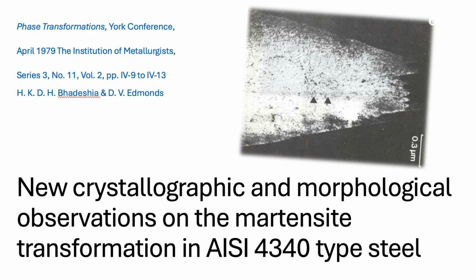Twinning. The sources found twinning within the plates. Yes, twinning is another way crystals can deform or accommodate stress. It's like creating a mirror image of the lattice across a specific plane. A stress relief mechanism. Exactly. But the sources found that twinning was only partial, it didn't always cross the entire plate. And critically, it mostly involved just a single variant, a single type of twin plane.